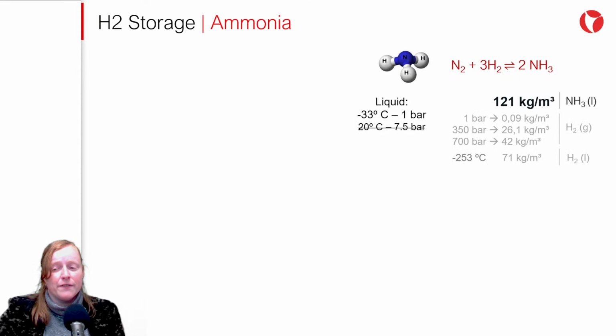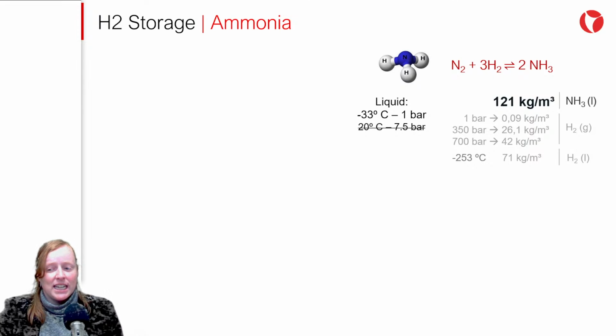It's interesting to note that the volumetric density of hydrogen achieved with liquid ammonia is significantly greater than that of hydrogen, which, when taken to the liquid phase at negative 253 degrees Celsius, reaches a density of 71 kilograms of hydrogen per cubic meter versus the 121 kilograms per cubic meter achieved with ammonia. In other words, with ammonia, much less volume is required for the same amount of hydrogen, without the need for extreme conditions. This is what makes it so attractive for use in the storage and transportation of hydrogen.